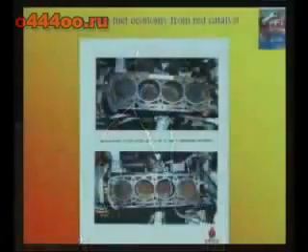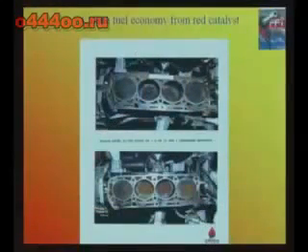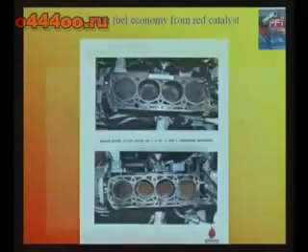It's not the pill that you are selling. It's not the pill that your customer is putting in the fuel. It's what happens to that pill after it dissolves, when it gets in the combustion chamber and goes through the flame combustion. It's deposited on the piston face and fire deck, and that red coating is the source. I've done this: you can take that piston out, pass a hexane-air mixture over it, and that piston will give 100% conversion to carbon dioxide. And a clean piston will give 0 conversion to carbon dioxide. It is catalytic. Okay? So that's what it does.